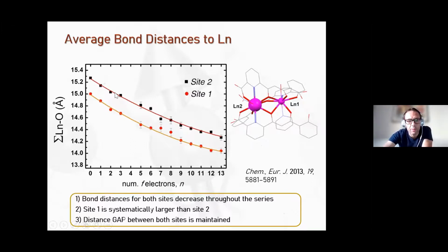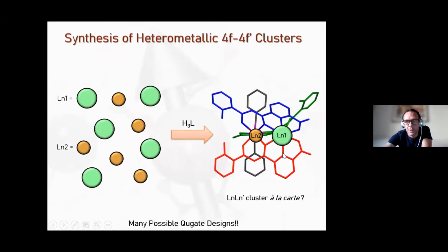So even if in both sites we see the lanthanide contraction, this gap between bond distances from one site to the other is maintained throughout the entire series. So there is one position on this scaffold that favors larger metals compared to the other position. Of course, this can be exploited to produce in one-pot reactions heterometallic lanthanide systems as long as we mix together two metals that have different sizes, because the system is then going to select the larger metal to put in one position compared to the other position, which is going to be reserved for the smaller metal.